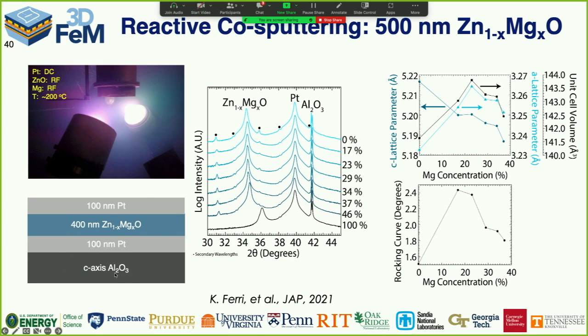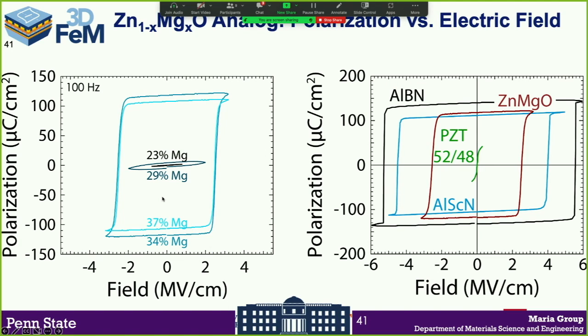I'm showing here data grown on sapphire single crystals, but we've also grown this on silicon and on polycrystalline tungsten. And what you see is that you get beautiful orientation. The material is another card-carrying ferroelectric. Here, though, look at the magnitudes of the fields required for polarization reversal. Instead of being 4 to 6 megavolts per centimeter, it's under 4 megavolts per centimeter. So that's helpful in terms of getting to a 1 volt device.